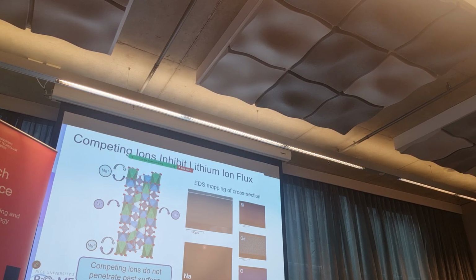When you look at the bottom at the end of the experiment, we see the red one is the sodium. It accumulated in the top layer, as we speculated and as we found by molecular simulations. This interfered with the partitioning of the lithium, so the lithium cannot go over. So I think the solid state electrolyte is really an amazing transport mechanism. In the paper we described the energy barrier and the mechanism of what's happening there.